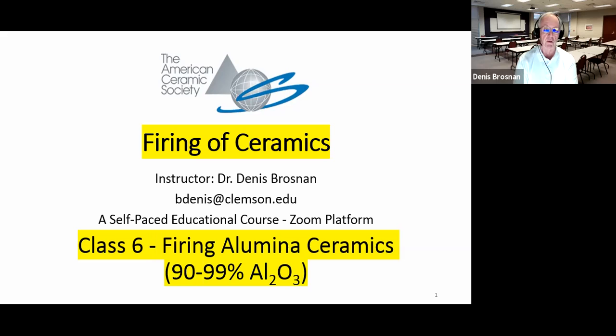These ceramics are typically graded in sizing to achieve the maximum density and pressing, and then they're fired to meet the product standards that there are for these types of products. Now, today we're going to talk about two products, and we'll talk about compositions around 95 or 96% aluminum oxide and lower. And those are products where a glass phase is involved. And of course, alumina or corundum is the major mineral that's present. But as you can guess from the phase diagram, mullite is also present.